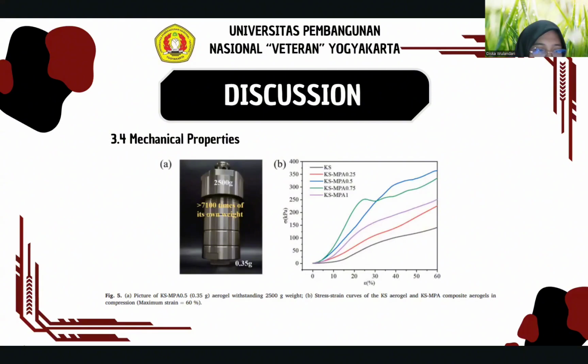0.5 showed a significant increase to 364.9 kilopascal, higher than several reported aerogels. However, with higher MPA content, compressive strength decreased due to the excessive nanosheet embedding, which damages the pore wall structure.